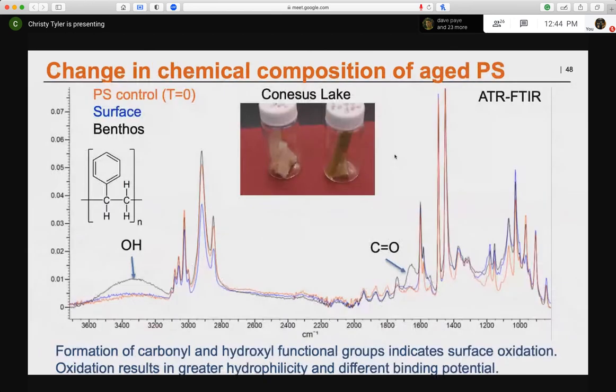But we also want to know chemically what's happening to the surfaces. So my students were also doing spectroscopic analysis of these plastics before and after aging. In all of the next 4 slides, you can see that the spectrum in orange to reddish orange is the control, so this is polystyrene before it is aged. In the blue, it's always going to be the sample at the surface, these being swatches, and the black is the benthos.